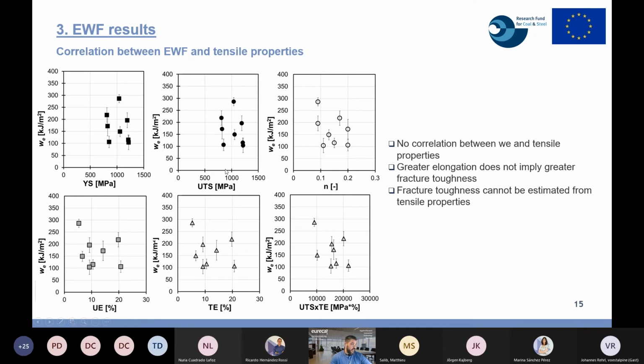But we can see here that there is no correlation between the crack propagation resistance and any of these parameters. In the traditional way of thinking, the materials with higher elongation or with higher strain hardening are supposed to show greater fracture toughness. This is not true. We can see that in advanced high-strength steels, rather on the contrary, often this trend is the opposite. So steels with higher elongation can show lower crack propagation resistance. The important point here is to highlight that fracture toughness cannot be estimated from tensile properties, and it should be properly measured in the frame of fracture mechanics.